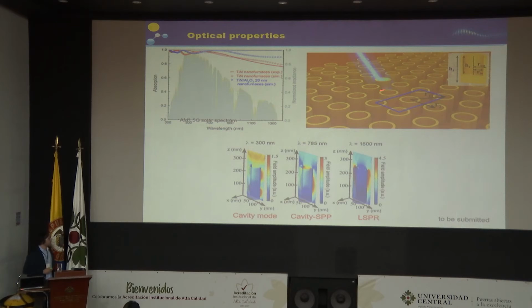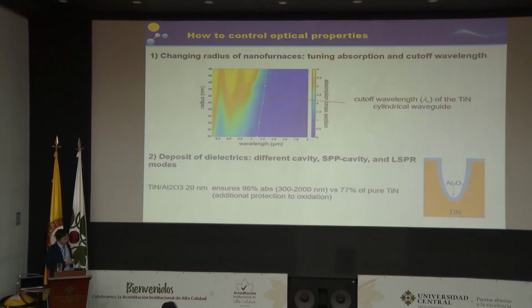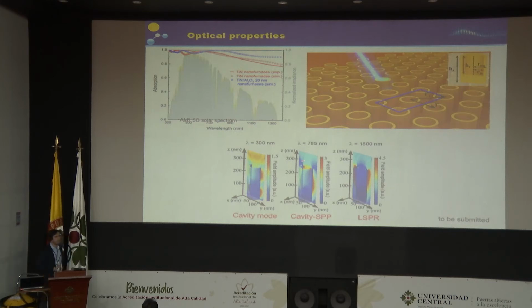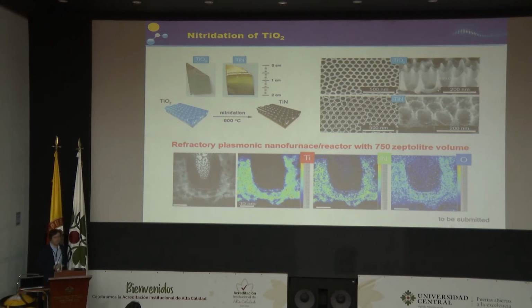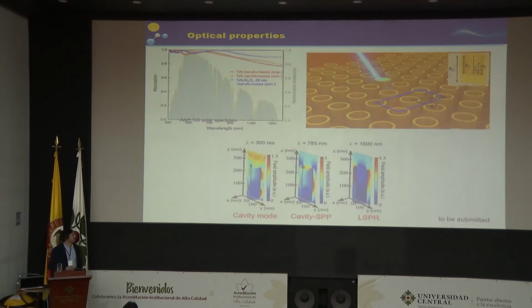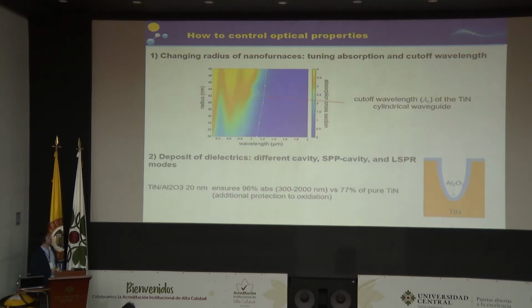What's happening here is similar to what happens in a photonic crystal cavity. Basically, light couples with this sub-wavelength cavity, so there is a formation of fundamental cavity modes inside this nanostructure, which also hybridize with surface plasmon polaritons in the walls of the nanostructure. The lossy nature of the titanium nitride and also the roughness of these materials produce a very high absorption in the visible and near infrared. After creating this unique structure, we started thinking about how we can tune the absorption.